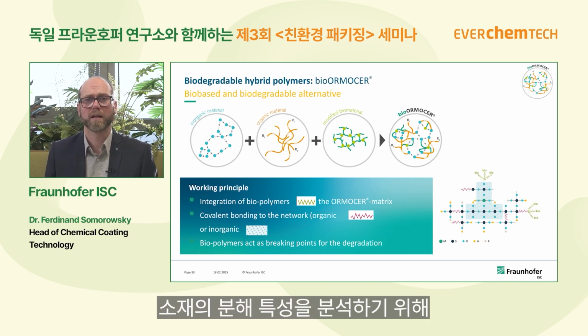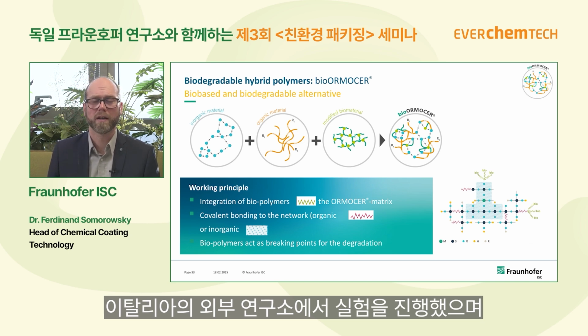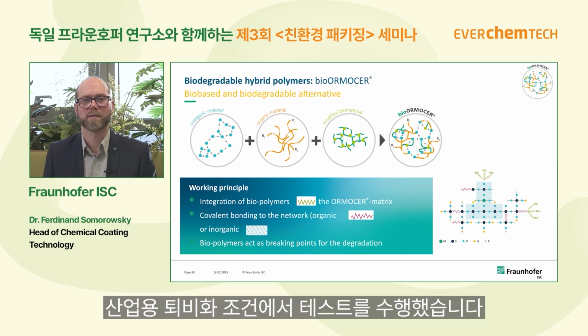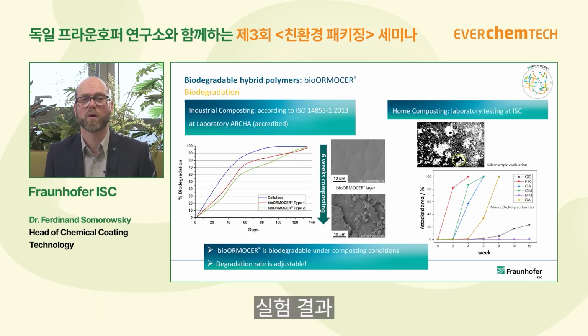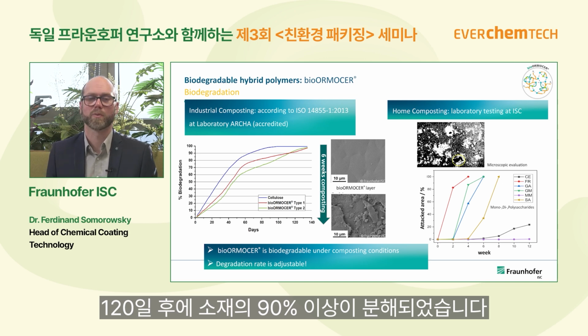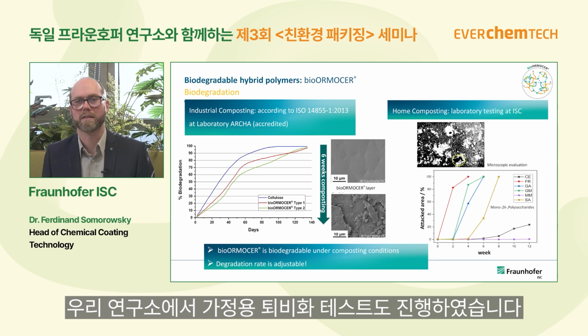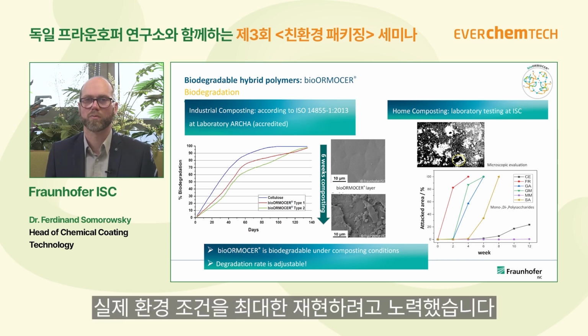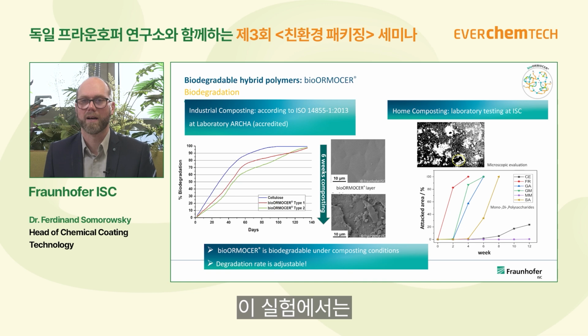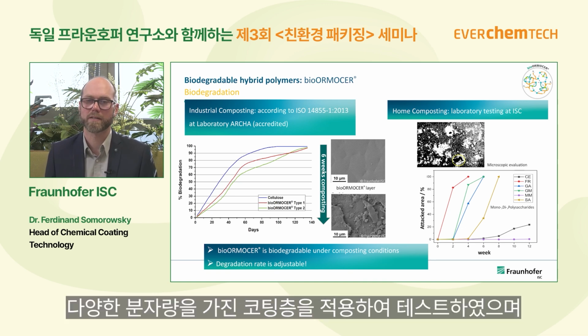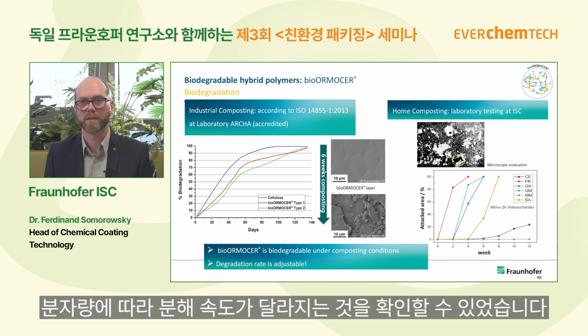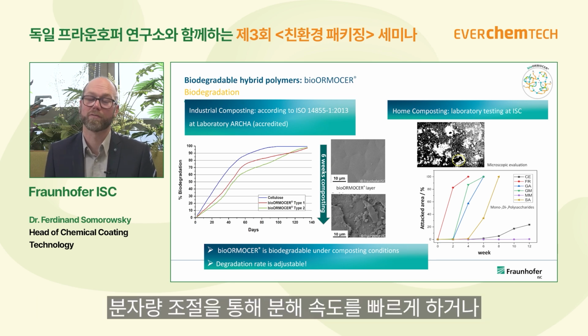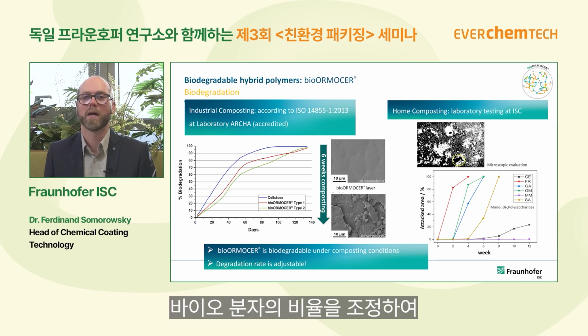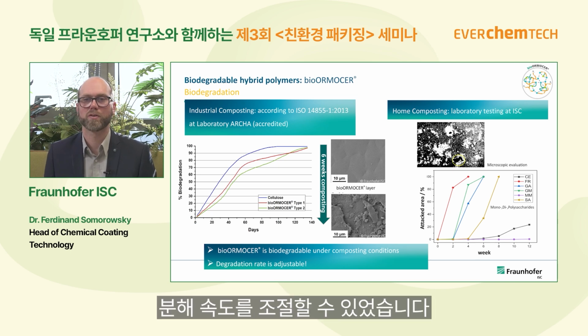When you look at the degradation in detail, we tested it with an external laboratory in Italy, and they checked the industrial composting conditions, and what we saw is that after 120 days more than 90% was degraded. And we also tested some home composting conditions. Our institute, we are not the expert for that, but we try to imitate the parameters. And what we saw also here in this example with different saccharide-based coating layers, depending on the molecular weight, we have also very fast degradation rates and can adjust the degradation rate a little bit by varying the ratio or varying the biomolecule.